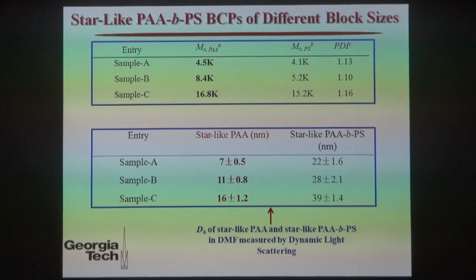So to demonstrate what I just said, we went ahead and prepared three star-like PAA block PS block polymers of different molecular weight for each. The molecular weights of the inner PAA block are 4.5, 8.4, and 16.8 K respectively. And we are looking at very monodisperse polymers because they were all prepared by atom transfer radical polymerization. If you look at the corresponding size for the inner PAA block, they are 7, 11, and 16 nanometers respectively, as measured by dynamic light scattering.